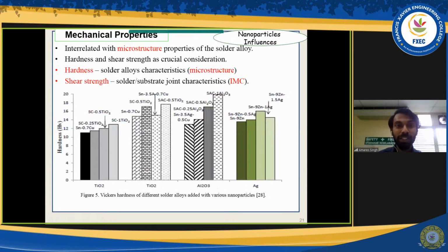So we can also see in terms of mechanical properties, additions of nanoparticles increases the hardness. But if you add a lot of weight percentage of nanoparticles, we will have a decrease in the hardness. This is because, again, of the non-refinement in terms of the microstructure.